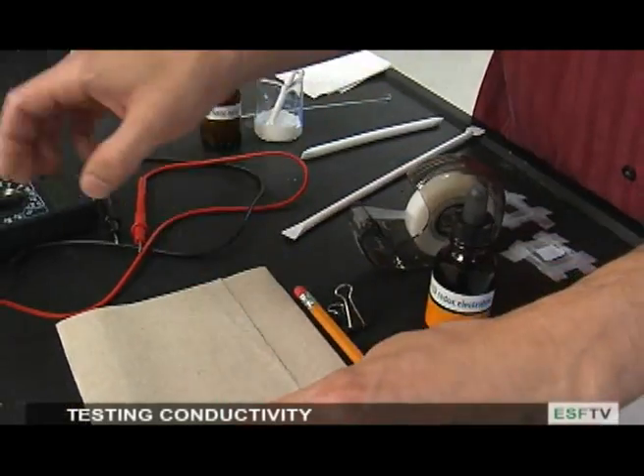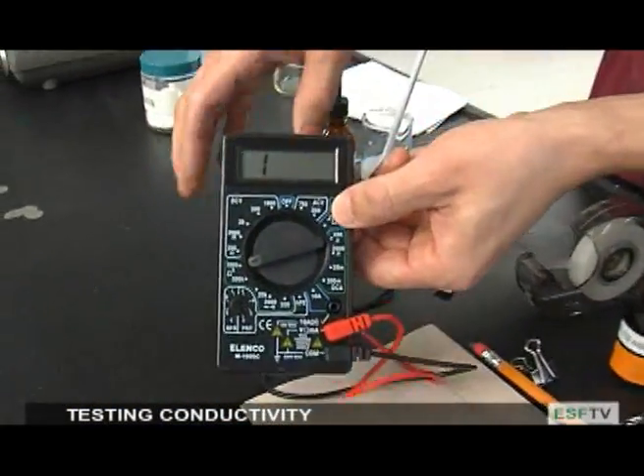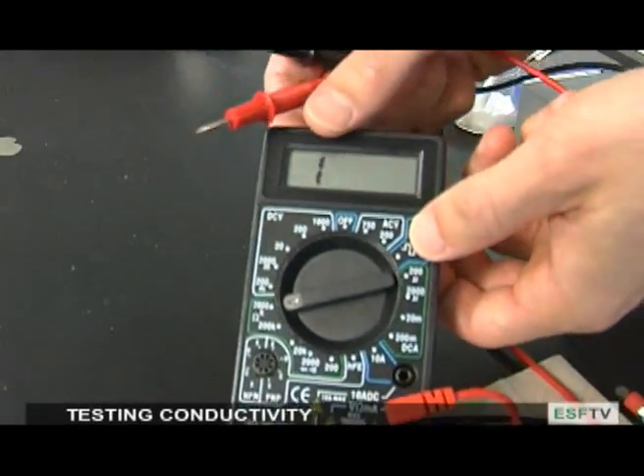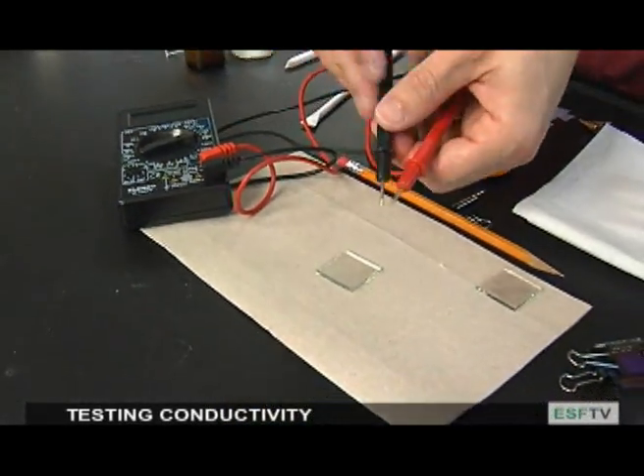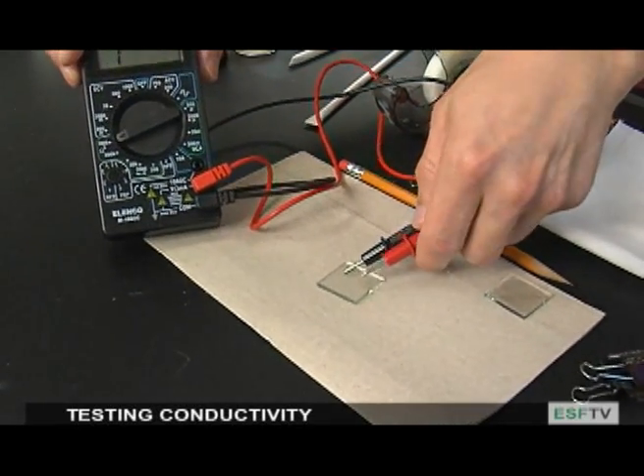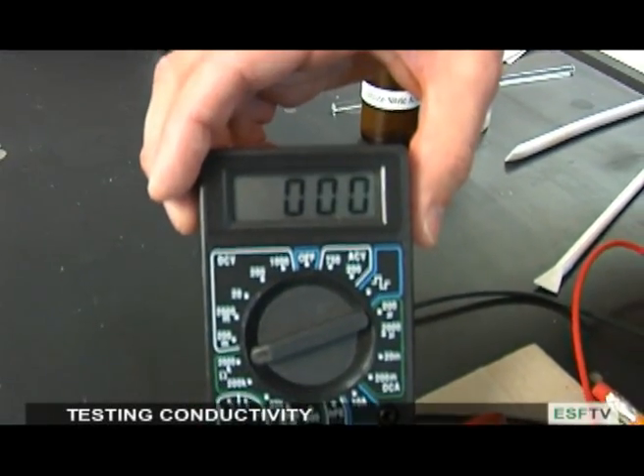To find out what side the coating is on, we're going to use a multimeter set to resistance. If we have the correct side, we'll see that the resistance goes to zero. We can see that the resistance now says zero, so we have the correct side facing up.